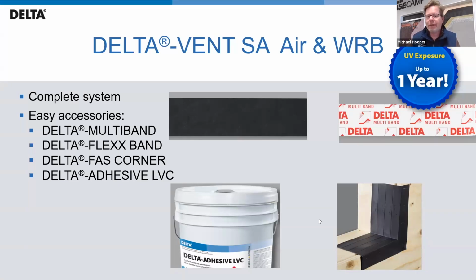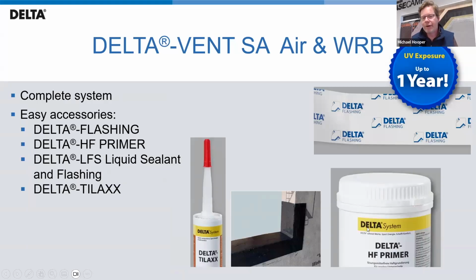And then we also have the fluid applied application, and this is done after your air barrier is installed. It's important to note that this is a silicone, and the reason why we use silicone as opposed to some other technologies in the market is material compatibility. A lot of STPEs and some products will create a hygroscopic condition with a product that's supposed to be hydrophobic, or make it hydrophilic when it's supposed to be hydrophobic. So it can take your air barrier that's supposed to prevent water from coming in and actually turn it into a wick and allow that moisture to come in. So in using silicone, we don't have that issue, but it's important that it's the right type of silicone.